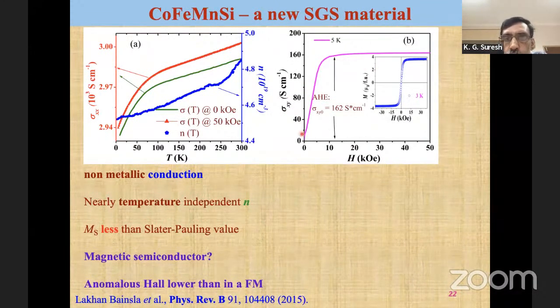From this Hall, we can actually identify the anomalous contribution. Anomalous contribution is a contribution that is coming purely because of the magnetization. That happens only in the case of a ferromagnetic material. It is not proportional to the magnetic field, which is the normal Hall, but you have what is known as a magnetization dependent Hall, that is called anomalous Hall. By looking at the anomalous Hall, the carrier concentration, and the magnetization values, you can get a reasonable idea that it is actually not going to be a half metallic ferromagnet.